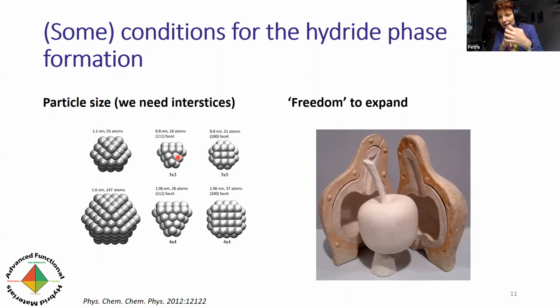Now, if we have a particle that is really confined physically and spatially in a space that is not free to expand, of course, the hydride phase once again will not form. So in order for us to determine whether it's the hydride phase or the metallic phase that is active, we can find a system in which we know that the hydride phase is unlikely to form, and compare that with other systems in which it may form, and see whether we can draw any conclusions with respect to the catalytic properties of the palladium particles.